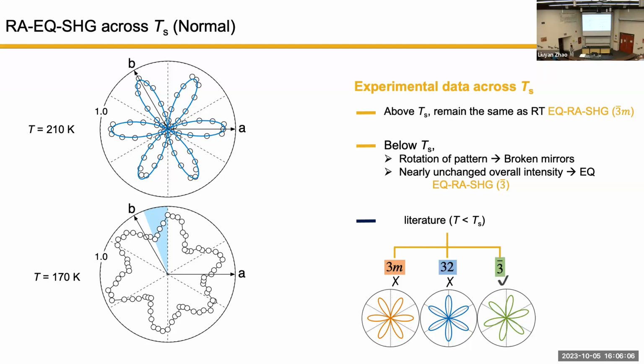Another example is called 32. The 2 means that instead of having a vertical mirror, I have an in-plane twofold rotational axis, and three of them. So if I have this spatial direction, then the pattern has to lock to that spatial direction. And the fact is that my pattern can rotate around. So that also rules out this 32. And bar 3 is a point group that has inversion symmetry and threefold, but does not have any spatial direction in the plane that forces the flower pattern to lock. So this is the optimal candidate to interpret our data.